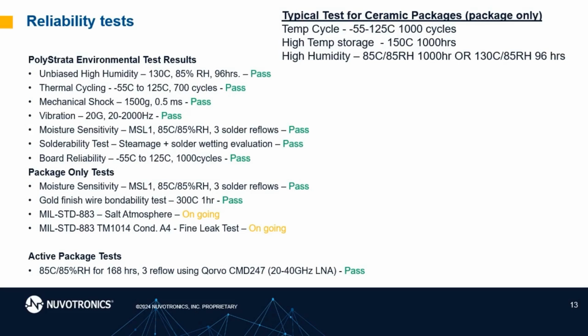We have built a small set of our packages with the Qorvo CMD247 die, bare die. It's a 20 to 40 gigahertz LNA, and we did run it through a typical 85/85 test for 168 hours. Ran it through reflow 3 times, and then retested and showed no change in performance. So passing well there too.